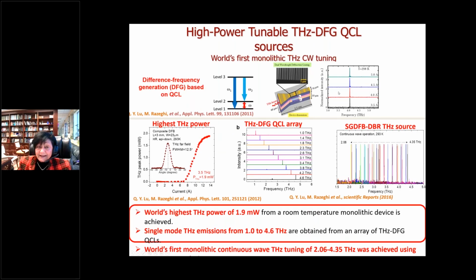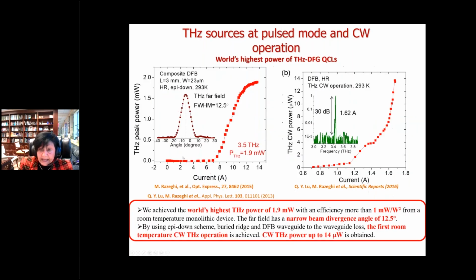So we demonstrated that, the world first. Not only did we demonstrate it continuously, but the beauty of that is, as it is the DFG, meaning difference frequency generation, as a function of temperature and as a function of the injection power, there is no jump, it is fixed. So for telecommunication, it's so important. Look at here, we have the very interesting 1.9. Now we have much higher power, at the same time the far field is only 12.5 degrees, and it is continuous wave again.